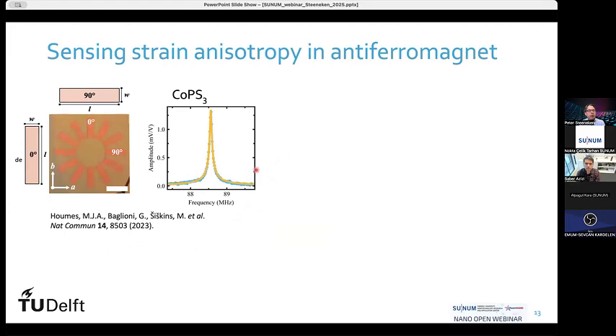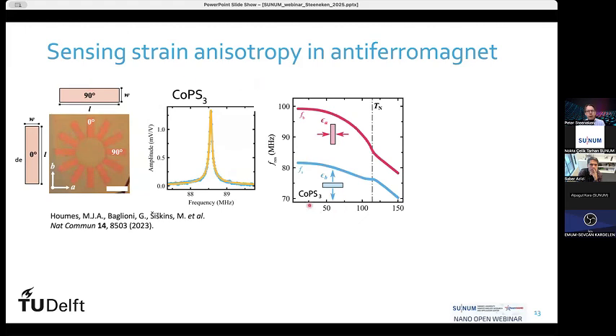Then we also started looking if we could look at anisotropic materials. So here we studied cobalt phosphor trisulfide, which is also such an antiferromagnet, but we created rectangular membranes. So instead of the circular ones that we had before, these are rectangular, and we made many of them, but we oriented them in different directions. So this is a single crystal. So that means that some of those rectangles were aligned with one crystal axis and the other ones aligned with another crystal axis. And the interesting thing about these rectangles is that the resonance frequency is mostly determined by the shortest direction. So what you see if you then start heating and cooling the material is that the resonance frequency really is different for the rectangles that are oriented horizontally from those that are oriented vertically.